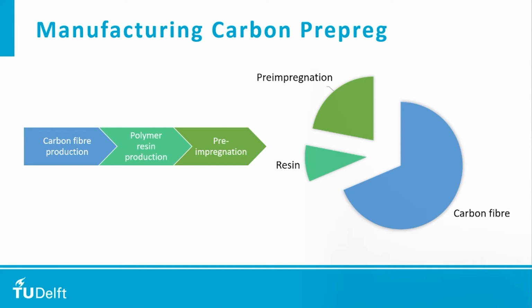Manufacturing of carbon composite prepreg comprises three major steps: manufacturing of carbon fiber, manufacturing of polymer matrix, and pre-impregnation of the fibers with the matrix. Of these three steps, carbon fiber manufacturing is the one that consumes the highest amount of energy, approximately 70% of the total.